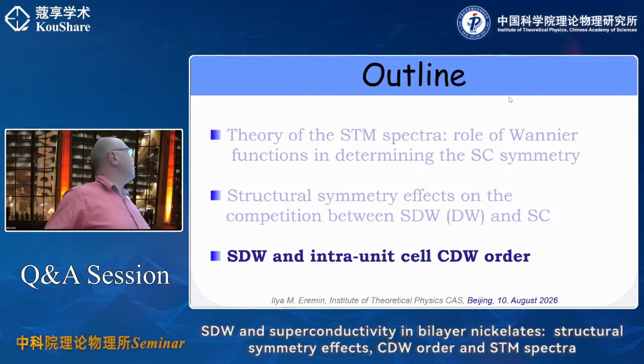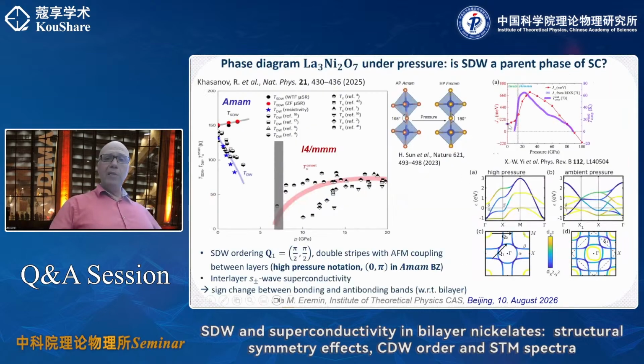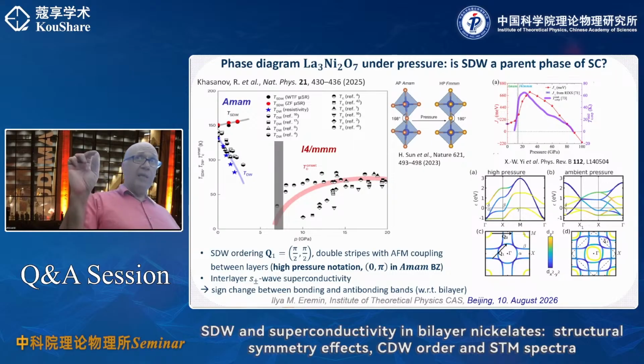So you see that here they claim that once they increase the pressure, the J-perp is increasing. Yeah. And that is partially also because once you increase the pressure, you also see in this calculation that NZ squared wants to become half filled. So in this regard, it's clear that it goes up. You understand why T spin density wave is going up, because J perp is going up. So that is somehow the interpretation. And you will also get it, by the way, in your weak coupling theory, if you just shift the doping. If you just assume that with increasing pressure, the filling of the NZ squared, by hand or by crystal field, increases such that it becomes more half filled, you will see that the spin density wave transition is going up. This is what you can try to see also.